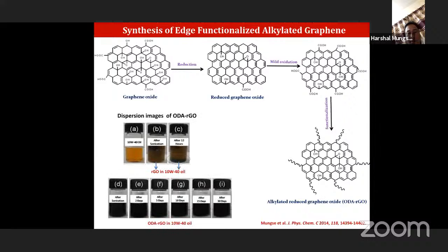You can see in this case, if we disperse only graphene, it is not dispersible. It is very difficult to disperse. That's why we can't use it as a lubricant additive directly. So for dispersion purposes, we have to functionalize this material, and after functionalization, you can see that even after 30 days this dispersion is very stable. So we can use it in tribology, or as a lubricant additive.